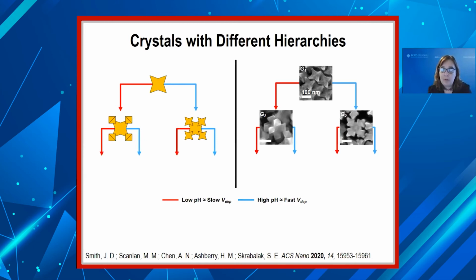So metal deposition is occurring preferentially at the 8 tips of our branched nanocrystals, but under slow deposition conditions that favor the thermodynamically favored shapes, we end up positioning polyhedral or octahedral shapes at those 8 tips.